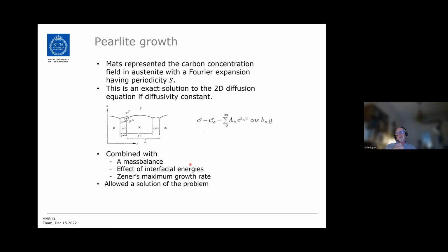This was used in his theory of pearlite growth. So Mats represented the carbon concentration field in austenite ahead of the pearlite front with a Fourier expansion with a periodicity S, which is the interlamellar spacing. And this is actually an exact solution to the 2-dimensional diffusion problem if the carbon diffusivity is constant and you expand then the concentration in a kind of series like this.